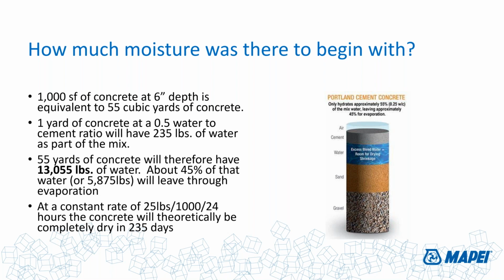That's a lot of concrete. 1 yard of concrete at a 0.5 water to cement ratio will have 235 pounds of water as part of the mix. So 55 yards of concrete will therefore have 13,055 pounds of water in it. That's a lot of water. That's a pretty good swimming pool of water.